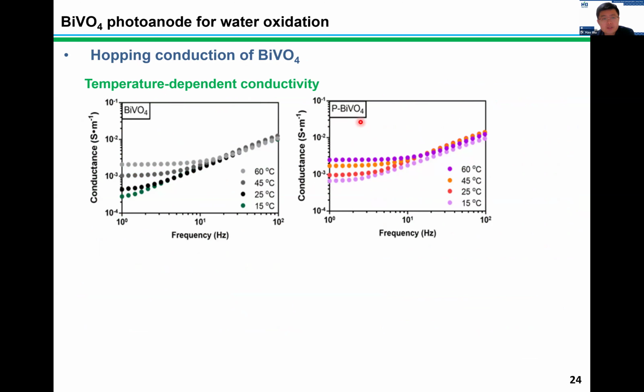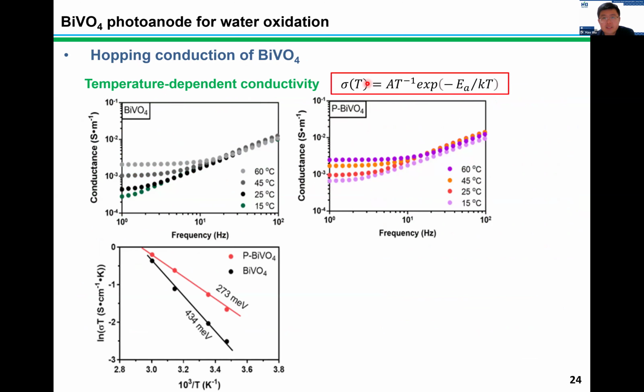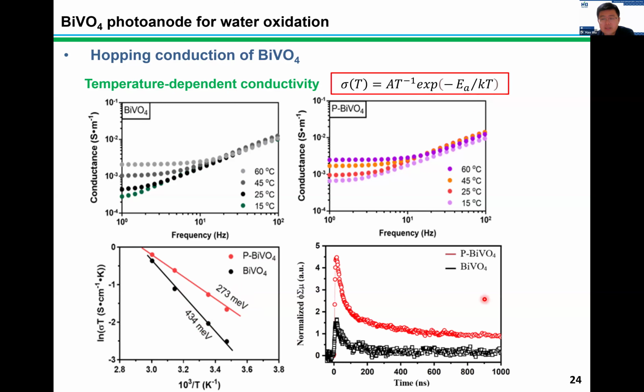But when we fit the conductance with the temperature following the Arrhenius relationship, we found that with the phosphorus doping, the activation energy of polaron hopping decreased from 434 to 273 milli-electron volts. It suggests that the polaron is easier to hop among the lattice of bismuth vanadate, which promotes the charge carrier transport behaviors. And to prove that, we also did time-resolved microwave conductivity measurements, and the results indeed suggest that upon the phosphorus doping, the carrier mobility increased by around 3.2 times.